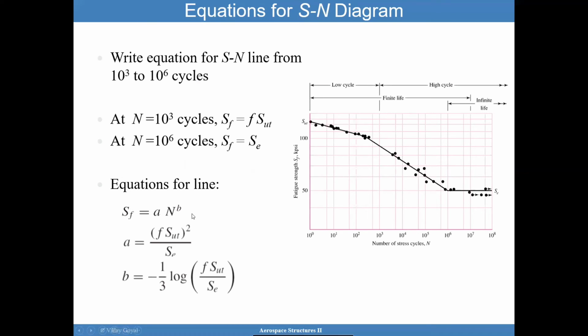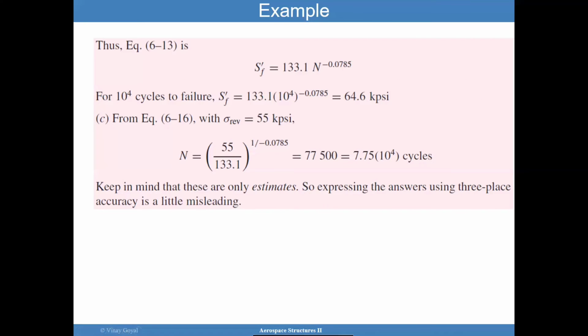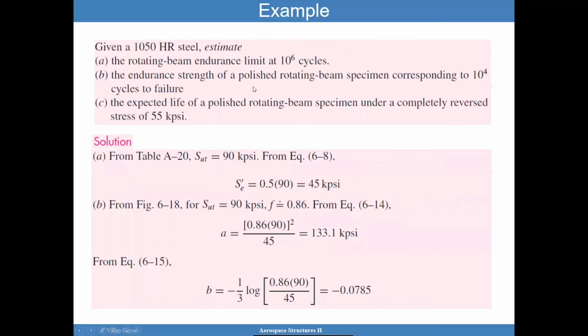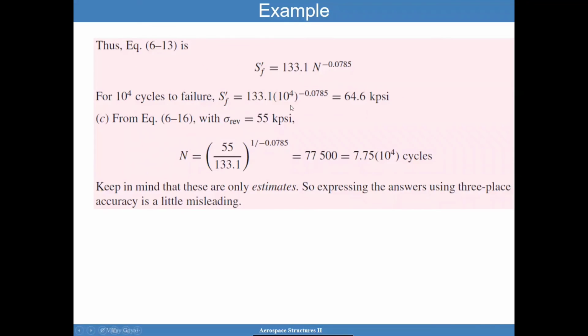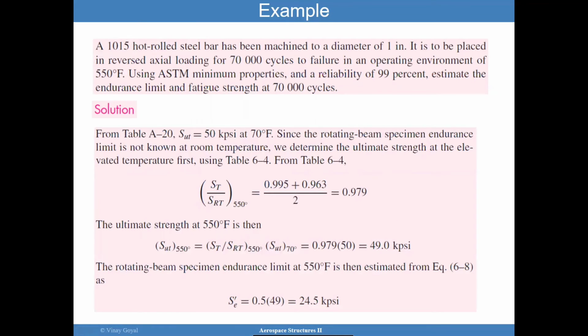Using this equation here. So here, that's the endurance strength due to 10 to the 4 cycles. And then for fully reversible, 55 KSI, I plug it into this equation for which I found the A and B exponent, and I get 7.75 times 10 to the 4 cycles. So these are only estimates, and recall that this is not going to be 100% accurate because of the difficulties with predicting cycle life and the scatter you may get in the test data.